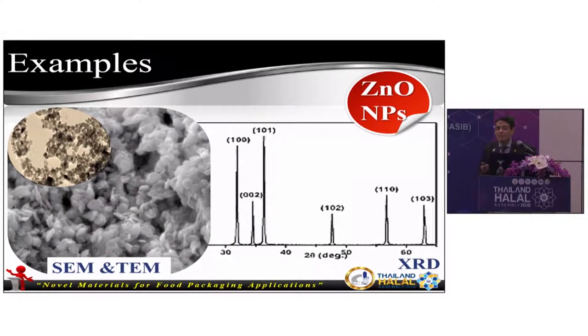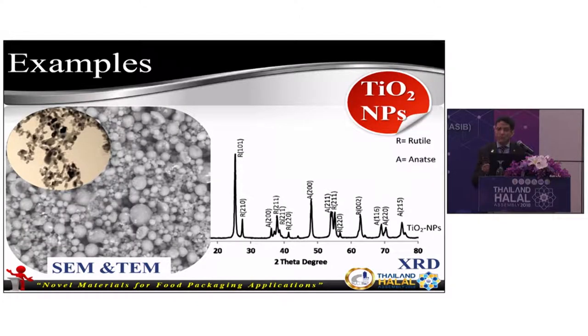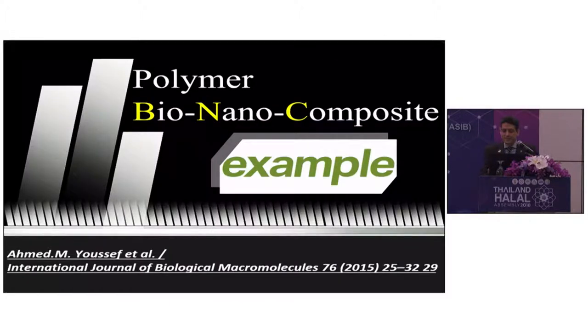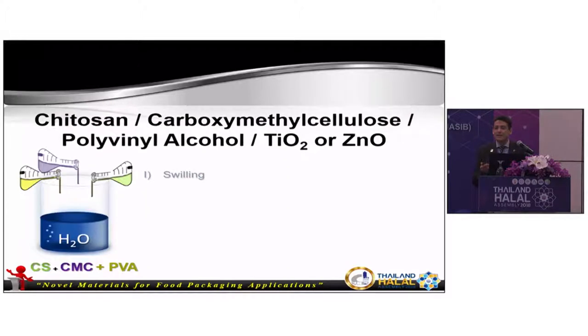We prepared zinc oxide nanoparticles by using a green method and confirmed the formation of zinc oxide nanoparticles by X-ray diffraction pattern, scanning electron microscope, and transmission electron microscope. Also, we prepared titanium dioxide and confirmed the formation of titanium dioxide in nano size by using X-ray diffraction, scanning electron microscope, and also transmission electron microscope.